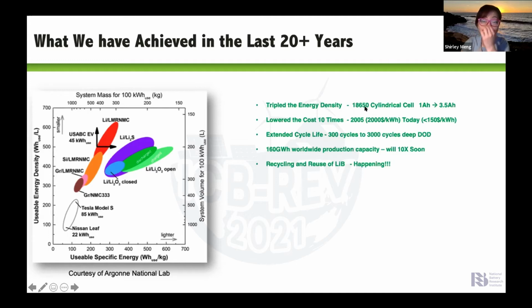In 1991, when the first 18650 cell was made, it was only 1 amp hour at 3.6 volts, so about 3.6 watt hours. But today you can easily go to 3.5 amp hours. So energy density for batteries has improved dramatically. Perhaps the most striking improvement is the reduction in cost. With economy of scale and improvement in manufacturing methods, we have lowered the cost more than 10 times. And we can now extend the cycle life to very long cycles, more than 1,000 cycles.